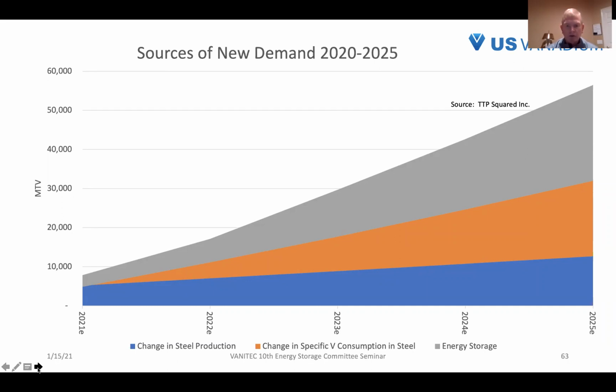So we won't see tremendous growth in vanadium consumption from increased steel production, but we do see accelerating increase in specific vanadium consumption levels. And that's really an economic decision. Putting a little bit of vanadium, typically half a kilo of vanadium, in a ton of steel, and increasing the yield strength 30 or 40 or 50 or sometimes 100% is hugely valuable from an economic standpoint. Steel is really the backbone of infrastructure that's required to industrialize developing countries to create economic opportunity.